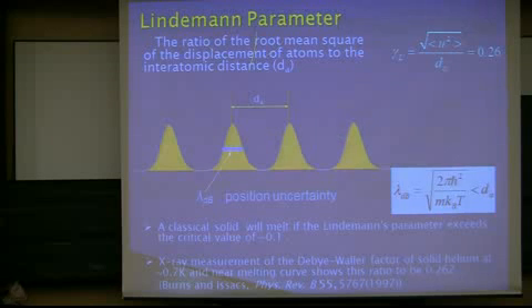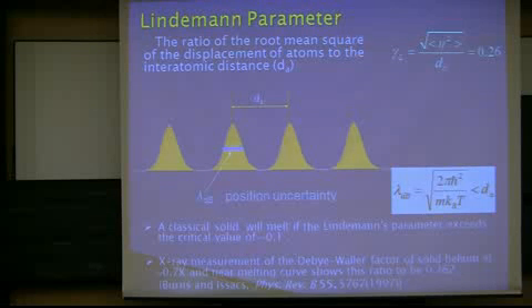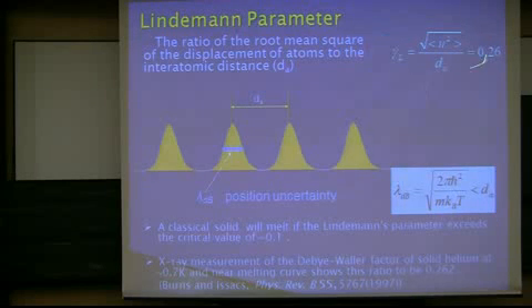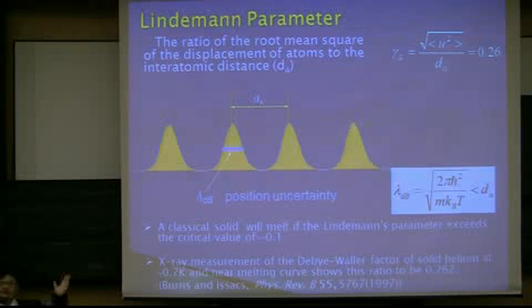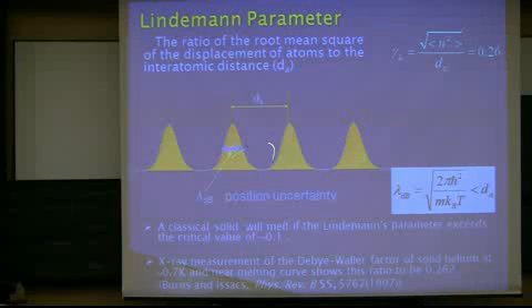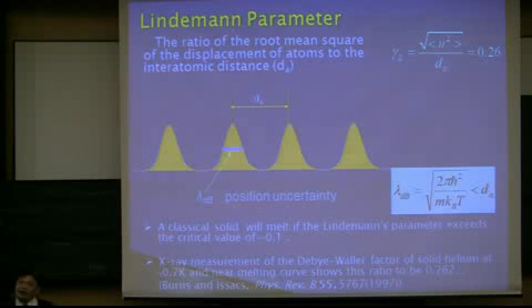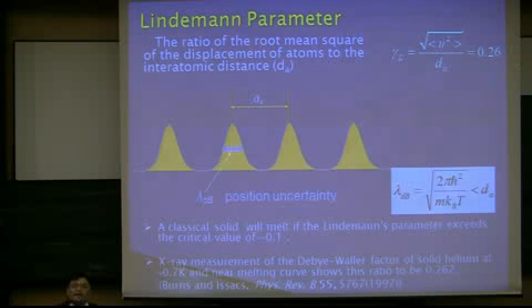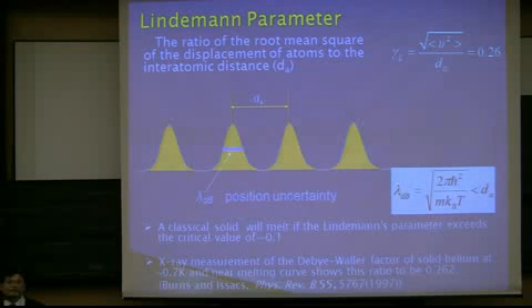Okay, that's the Lindemann parameter. The Lindemann parameter is simply the ratio of fluctuation with respect to the interatomic distance. For the solid helium case, this is the interatomic distance and this is the position uncertainty, which is very relevant when you are describing the fluctuation. But it is very surprising. It is surprising because the quantum fluctuation for the solid helium case is very close to 30%. This was found in the experiment and also predicted in the quantum Monte Carlo simulation.